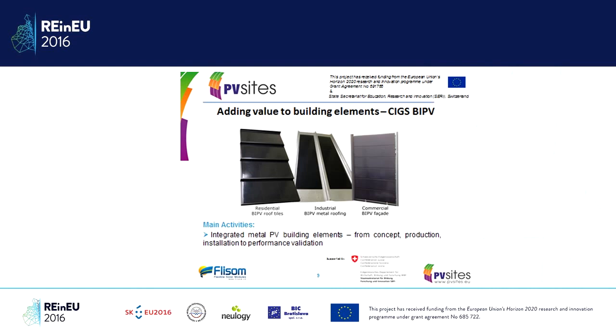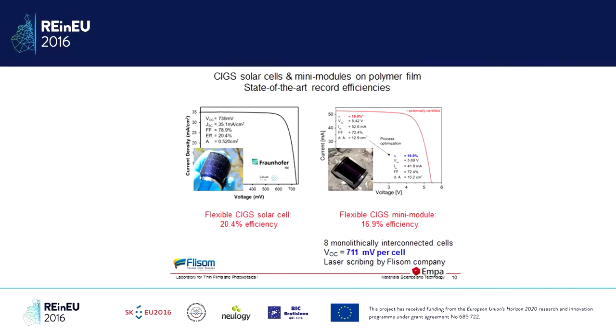So to give you the context, human hair thickness is about 50 microns. So what we are talking about is 1/10 of the human hair thickness. So that's what I was talking about. If you look at the energy payback time of thin film solar cells, which is CIGS and cadmium telluride, and you compare to monocrystalline and multicrystalline silicon, despite lower efficiency, you have shorter energy payback time. So this is a very good reason to consider that thin film solar cells would be very useful.